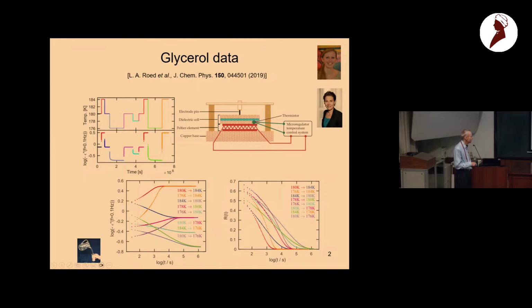And what you see immediately, and you can see it already here, is that for jumps to the same temperature, they look quite different. If this was a linear response, any jump to the same temperature and the normalized function would give the same function. But you can see they're quite different. You can see it here in the shape. So this is a highly nonlinear phenomenon, even for rather small jumps like 1 or 2 Kelvin, 1 or 2%. And the question is, how can we understand that?